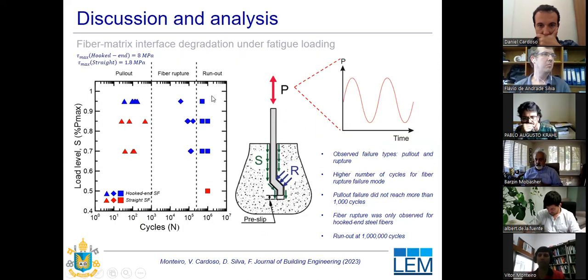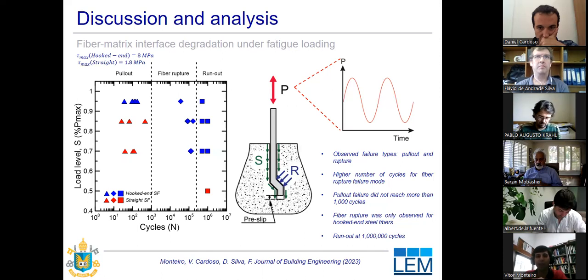So one of the main results in the interface degradation is that we could observe two major types of failure in this pull-out fatigue test. We could observe a pull-out failure or the fiber rupture failure. What that exactly means is that during the test, when we have a pull-out failure, we couldn't reach many cycles before failure. We could reach a maximum number of 1,000 cycles before the pull-out failure for both hooked ends and straight fibers. The pull-out failure is simply that the fiber is pulled from the matrix.